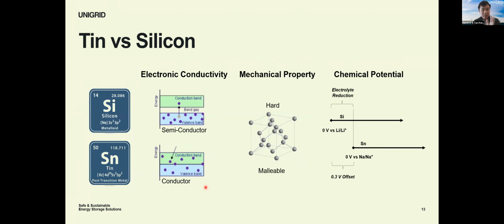Firstly, tin is a conductor, unlike silicon, which is a semiconductor. In silicon, you have to add a lot of carbon in the anode to make it work. Carbon is a nasty source of a lot of side reactions that you want to avoid. But in tin, we can remove all carbon additives from the electrode, so we don't have all these side reactions occurring. Secondly, silicon is very hard and very brittle. When it expands, you can't stop it. It's going to pulverize. It's going to break apart. That's where you lose your active materials and your capacity fades.